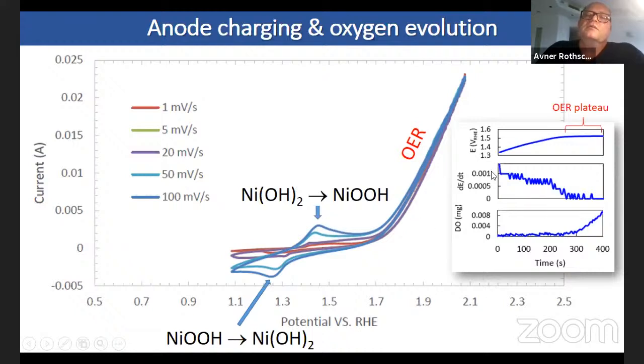And also, if you look at the charging curve, you see that once we fully charge the electrode, it starts to generate oxygen, which obviously is something we don't want. So we stop when we see this potential plateau. We verified with dissolved oxygen measurement that as soon as the potential starts to plateau, that's the point where oxygen starts to evolve, where below this point there is no oxygen evolution. So this gives us an easy handle when to stop the cycle.